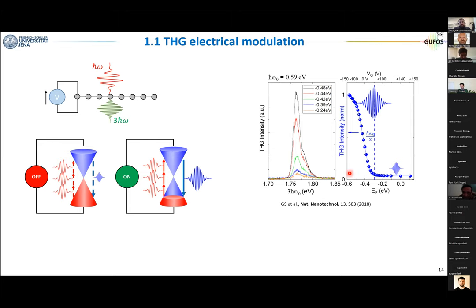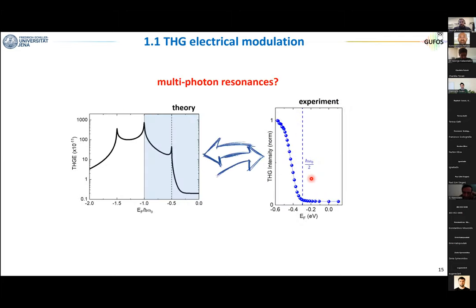But before I move on, I want to show one thing. I started from discussing this theory, where I say, okay, there are three very sharp resonances. And the first resonance is when the Fermi energy is equal to 2 times h bar omega, this one. And now we look at the experiments. And this line, that is exactly this condition here, is certainly not at the point where we have a resonance. So there is clearly a very big discrepancy between the theory and the experiments.